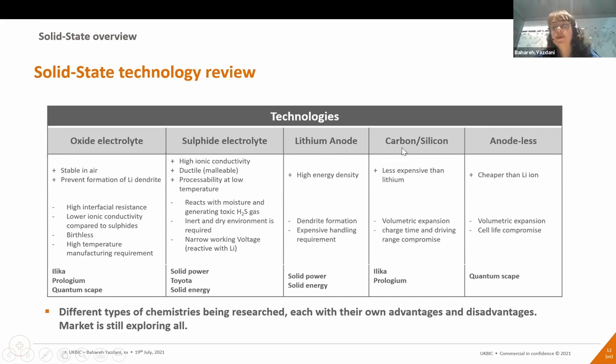So lithium ions, and some companies are still using carbon silicon composite for the anode side to make the manufacturing less expensive, and also to prevent the lithium metal handling issues. Some new companies, including QuantumScape, are also talking about anode-less manufacturing technologies, which is basically plating the lithium on the anode side, and then reabsorption of the lithium metal from the cycling, charging and discharging cycles. So as you can see, a lot of companies and different chemistries are being researched, and the market is still exploring different technologies. So there is a huge demand for doing research, exploring and finding which one is the best approach for